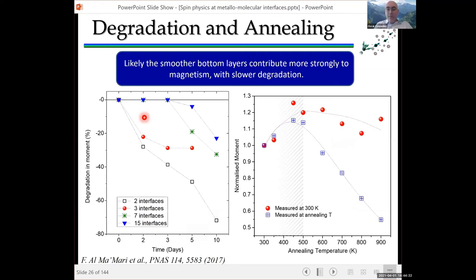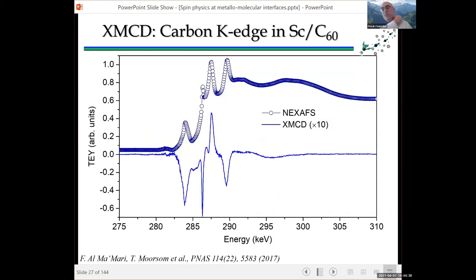You can recover it by annealing it to about 500 Kelvin, which is the temperature at which oxygen dissociates from C60. So you can remove the oxygen from the interface, and then you can recover at least partly this magnetization that you have induced. We did some extensive measurements to make sure where this magnetization was coming from.